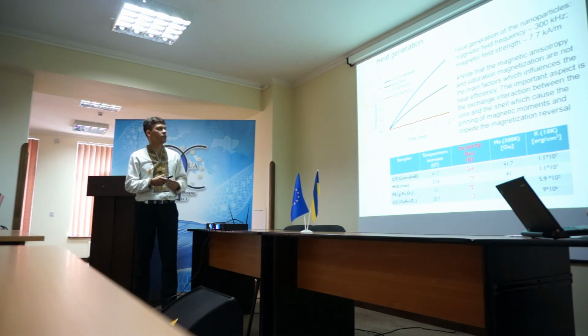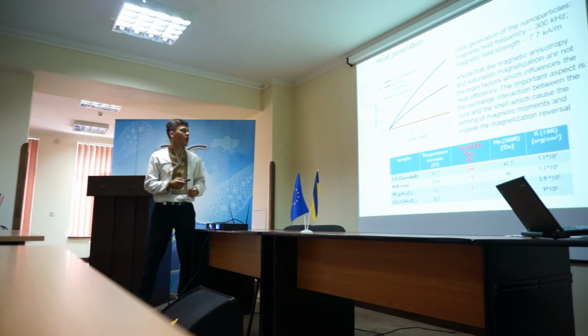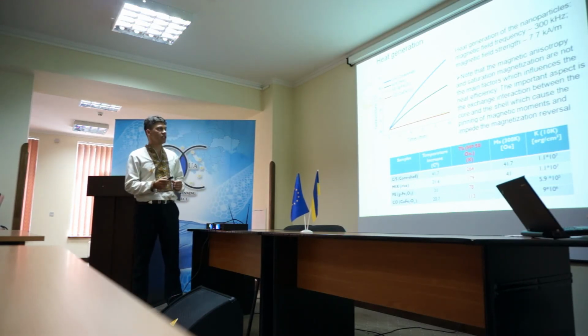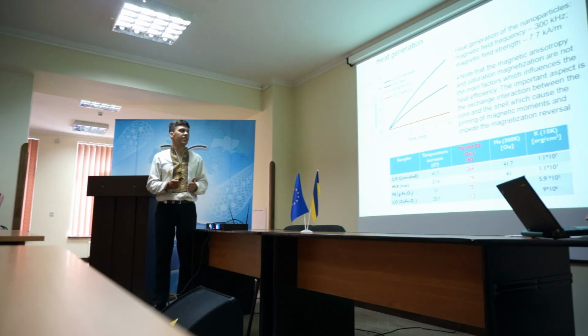And the most interesting is the result of the heating of nanoparticles. For obtaining this, we use a magnetic field frequency of 300 kHz with a magnetic field strength of 7.7 kA per meter. And as we can see from this picture, there is a small value for the pure manganese and cobalt ferrite nanoparticles, but a very significant increase in the mixed nanoparticles due to dipole-dipole interaction, and the highest value we obtain for the core shell nanoparticles. What is very interesting is that magnetic anisotropy and saturation magnetization are not the main factors which influence the heat efficiency.